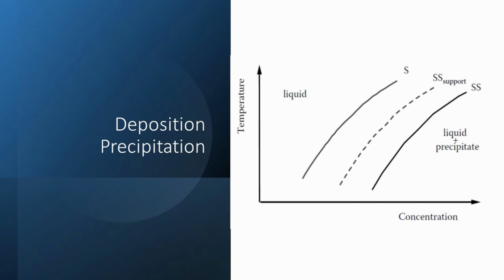First, interaction between the soluble metal precursor and the surface of the support is required. In such a case, the supersaturation curve shown in the figure is shifted towards a lower concentration in the presence of support, curve SS support. And second, the concentration of the precursor must be maintained between the saturation and the supersaturation curves to avoid precipitation in solution.